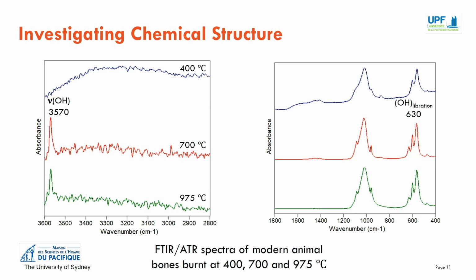Other noticeable changes are the decreased intensity of the spectral region from 1700 to 1350 wave numbers, assigned to a range of components including proteins, lipids, and carbonates. The decrease in the intensity of these features is a result of the destruction of the organic matrix, with the removal of lipids, degradation of proteins, and change in carbonate bands reflecting the change in the bone's inorganic matrix. These observations concur with those collected with laboratory instruments, confirming the transferable nature of this method.